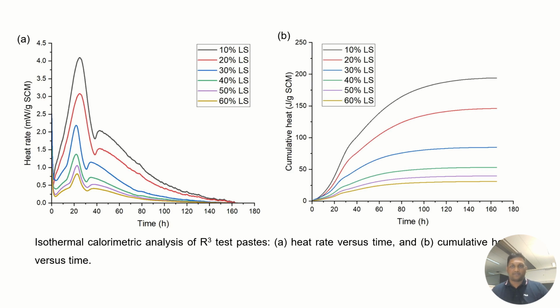The amount of heat released in early hours is related to the formation of hydration products and bound water. Firstly, a high heat burst was observed within 15 to 20 minutes of the mixing of the dry material in the alkaline water, due to the wetting and dissolution, followed by a dormant period. Secondly, the formation of ettringite is induced in the dormant period at 3 to 4 hours due to the dissolution of the reactive sulfate, aluminate and carbonate ions.